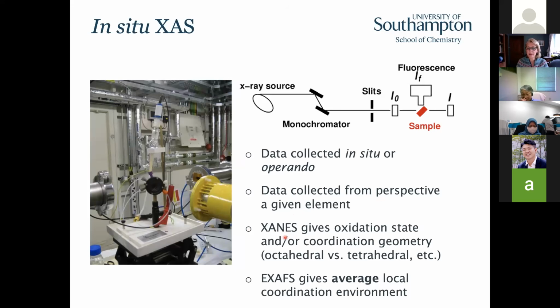I'm going to show you in a moment a slide which gives you a picture of the overall spectrum, but we break it up into two parts. We call this part the XANES, and that's the X-ray absorption near edge structure. That's the energy of the transition. And there are a few extra features in that which can tell us about the oxidation state and the coordination geometry. So for example, if you have a metal ion in an octahedral or a tetrahedral site. The EXAFS, the extended X-ray absorption fine structure, is the rest of the spectrum. And that gives us the average local coordination environment. And it's really important that we remember that this is the average. It's the per atom average.